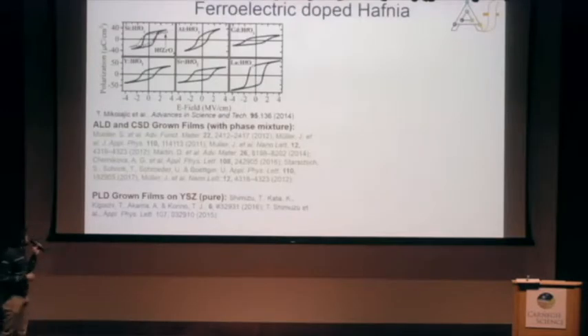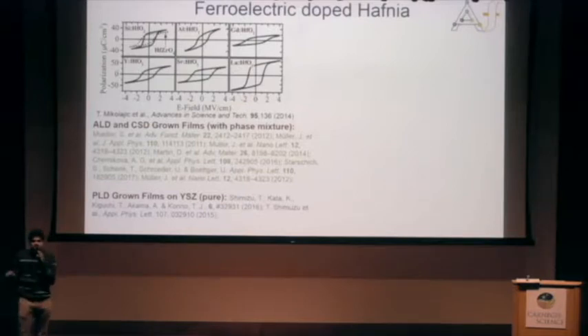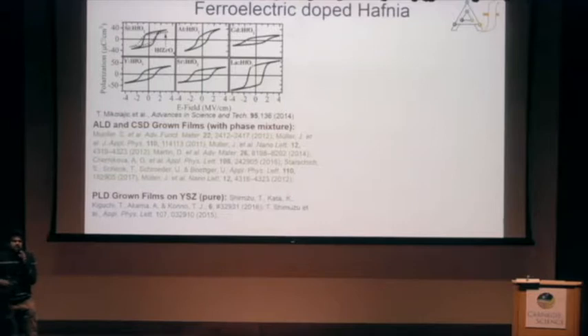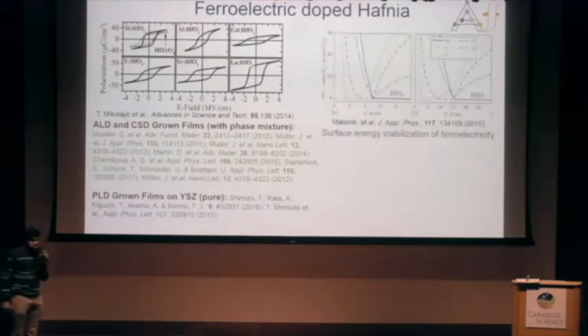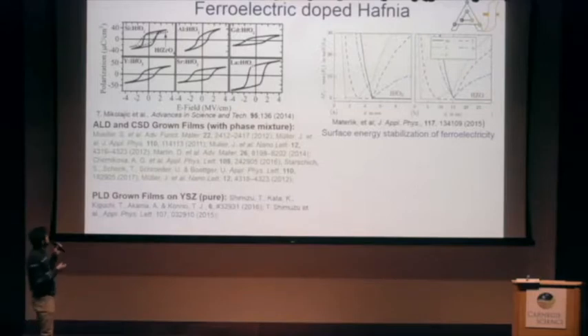Since 2011, it's now a joke that you take any crystalline hafnia below 10 nanometers or so, dope it with anything, and it becomes ferroelectric. So there have been several demonstrations based on different techniques and with different dopants. Insights, as always, come from theory as to what stabilizes this polar orthorhombic phase.